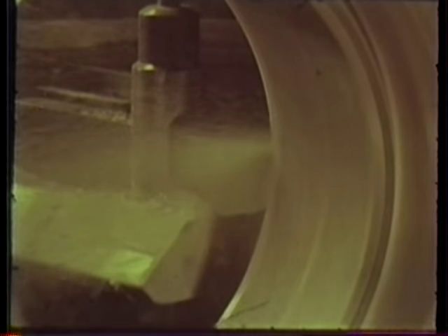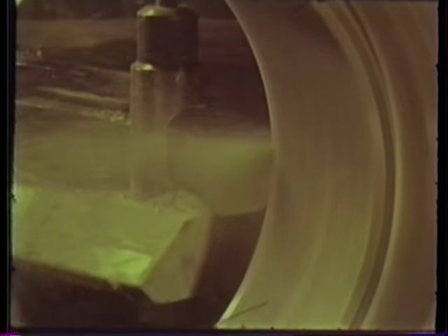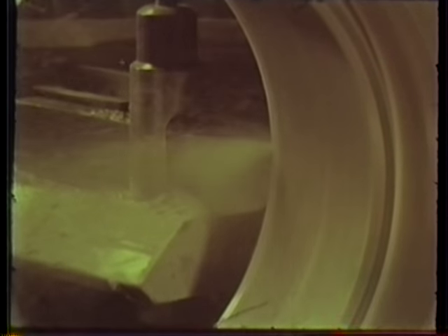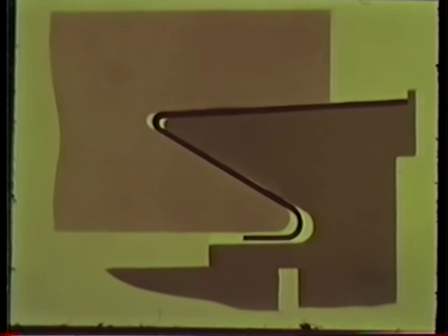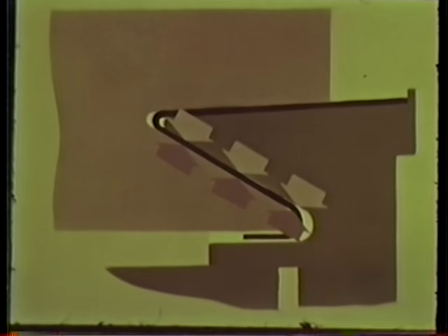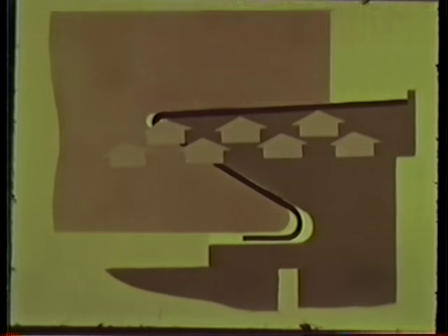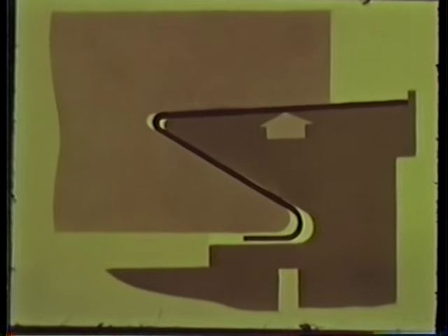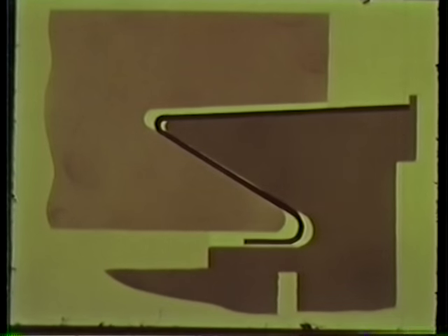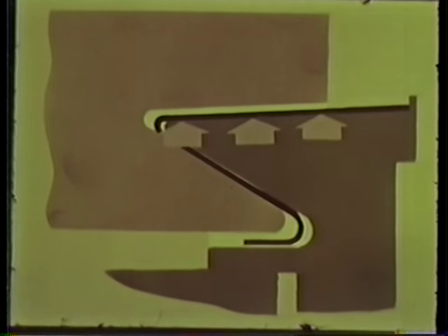This step must be precise, regardless of whether the commutator is to be of the V-bound type or of the arch-bound type. With the V-bound commutator, most of the pressure from the cap and shell is carried on the 30-degree surface, but the amount carried on the 3-degree surface is very critical. Either too much or too little pressure at this point will cause roughness in the overhang area. The arch-bound commutator is inherently smoother than the V-bound because there is no pressure at all on the 3-degree surface.